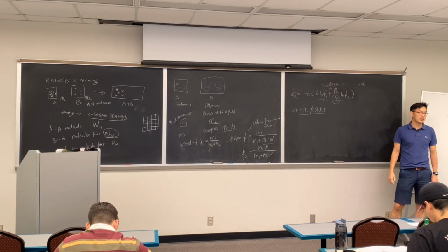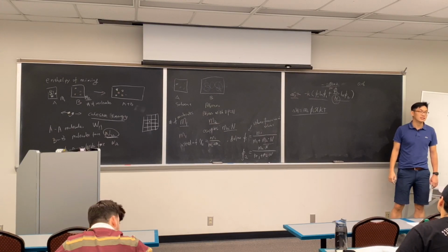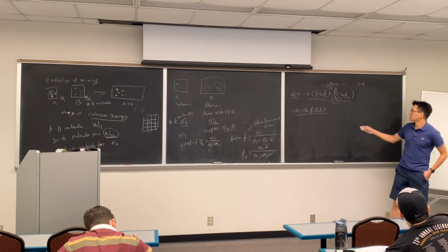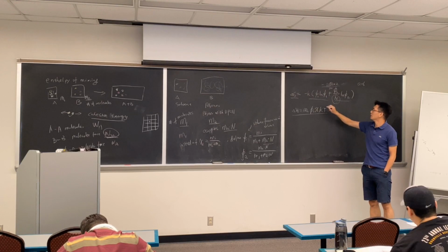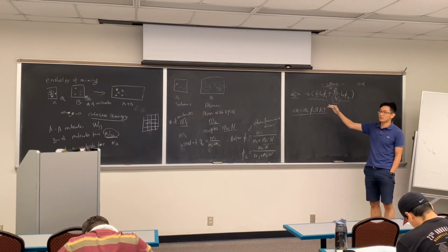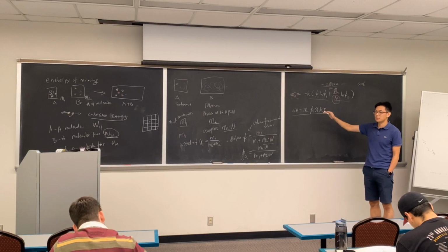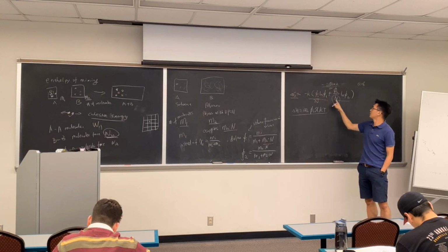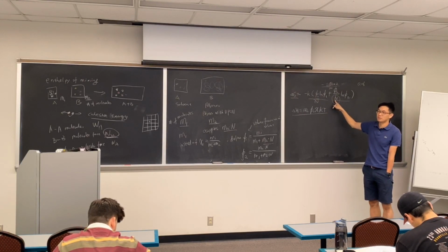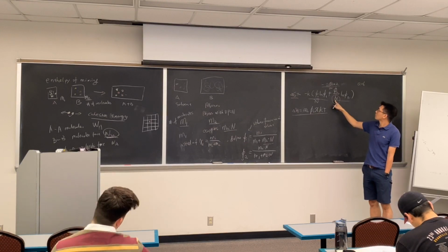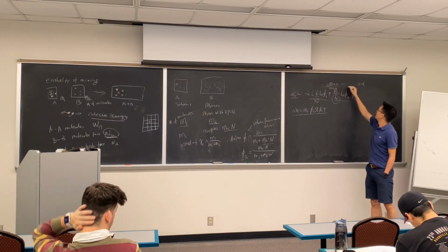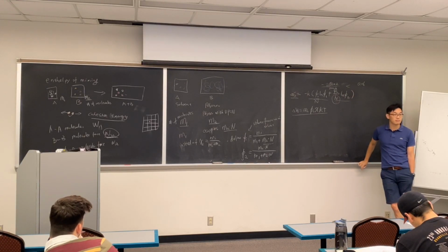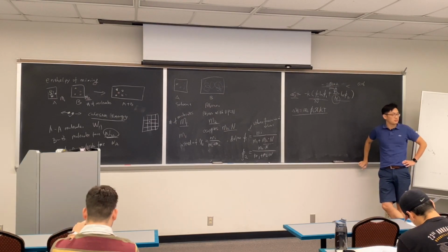This will drop to a similar level. Now, as you can see, polymer mixing is not totally entropy driven. Polymer-solvent still is, because the solvent still has a large contribution. But we can start seeing what comes next. If you mix a polymer with another polymer, the entropy contribution for both phase A and phase B is going to take a hit from the number of permutations. If you divide this by 1,000, you can see the enthalpy will be larger than the entropic drive. So enthalpy starts to play a critical role in polymer mixing.